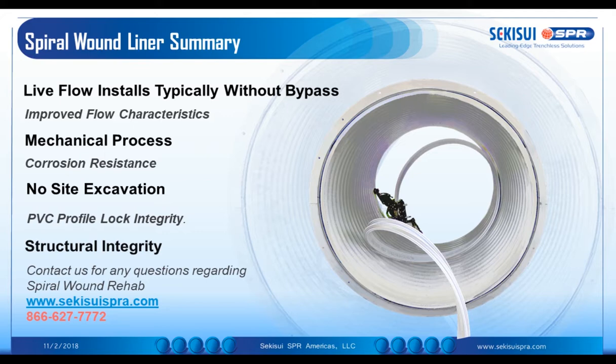Now, grouting only applies to the SPR technology, and depending on the diameter, we are actually able to use the ASTM flexible pipe design as well, in accordance with ASTM F1741. And if that's the case, we can also use cellular grouts with a low strength, and so there are different requirements depending on the project.